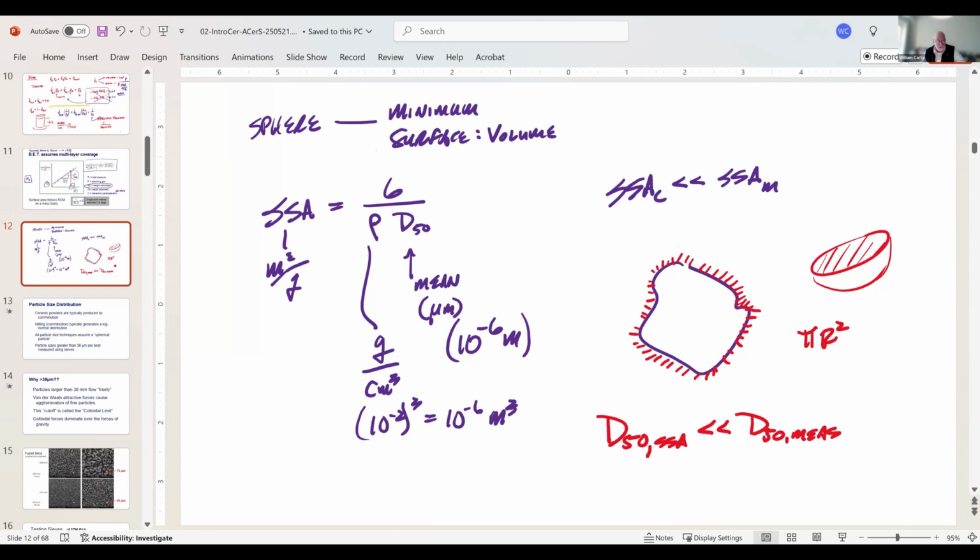And your particles are not spherical, with very few exceptions. And even if they're spherical, let's say you have a golf ball, the surface of a golf ball has all the dimples in it. That increases its surface area. Okay, so just keep in mind, they are independent measurements, surface area, particle size distribution, and density, but they can be used to understand more about your powders.